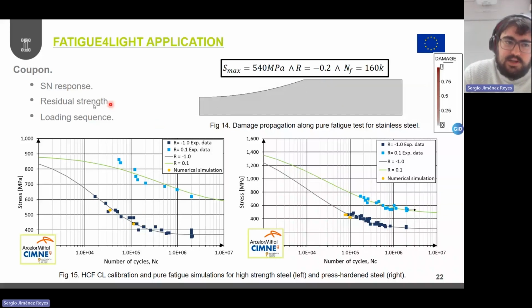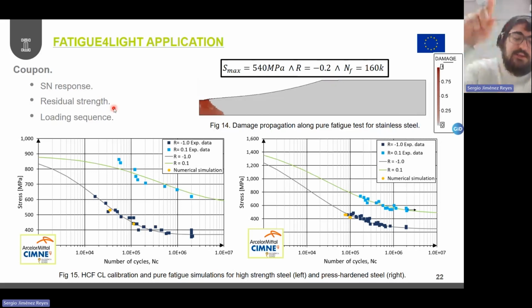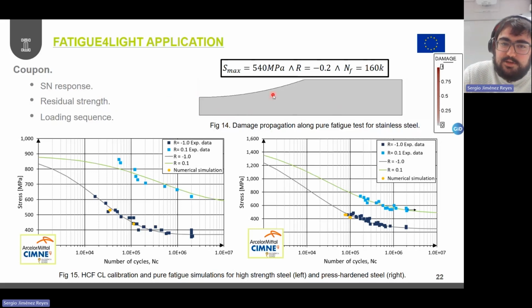But we can also work in other more complex scenarios in which we follow a similar approach to the one that I was presenting previously. So I will not present anything about this, where we first of all apply several cycles, and then we move towards a pure tensile test, and we observe the strength degradation associated to that material as a function of the amount of cycles being applied. And I'm including this chart here corresponding to this stainless steel that I was previously characterizing, just because it's interesting to observe one of the main features of this constitutive model, which is the ability of studying this crack propagation in the geometry being studied. In this case, this is just a coupon sample, but this applies to other cases.